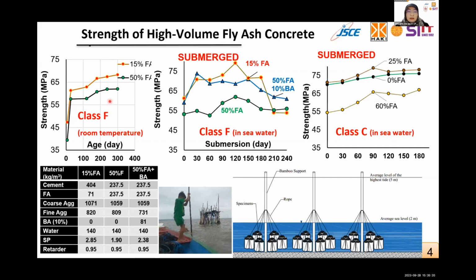At room temperature here, with 50% cement replacement, class F fly ash shows less strength than 15% fly ash concrete. And the condition is the same as submerging in the seawater until around 8 months. However, if we apply bottom ash to replace around 10% of sand, the effect of internal curing results in a positive contribution to the strength. It seems that the pozzolanic reaction is guaranteed by the internal curing or internal moisture. And here is the class C fly ash, as expected, as the previous presenter also showed.